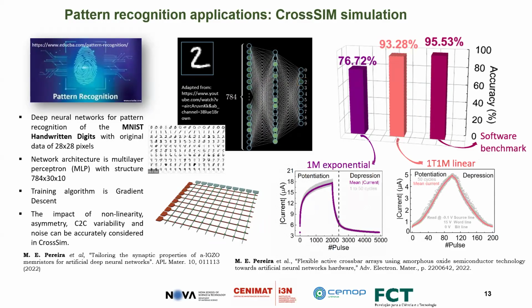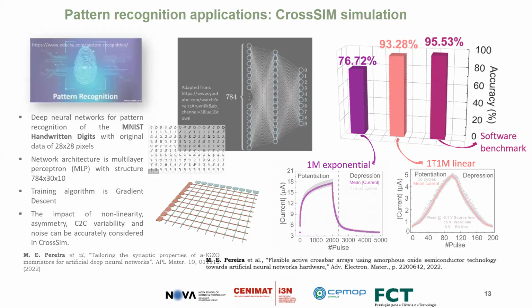And then, for deep neural network application, for pattern recognition, we use MNIST handwritten digits here, and examine both the exponential and the linear response to see the difference in accuracy. So this is a software benchmark, as you can see, and here we could also examine the impact of device nonlinearity, asymmetry, cycle-to-cycle variability, and even noise. That we also published. The noise level of the area-dependent device is extremely low, especially random telegraph noise, compared to the filamentary devices.